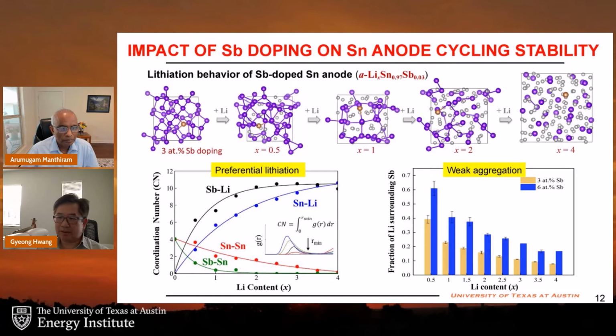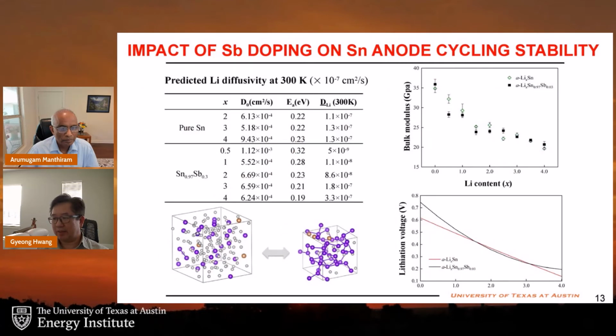As summarized in the next slide, we have also compared lithiation-induced changes in the electrochemical, transport, and the mechanical properties between the antimony-doped and the pure tin system. So our study highlights the importance of a low concentration and the uniform distribution of antimony in order to obtain desired properties of antimony-doped tin as an anode for lithium-ion batteries.